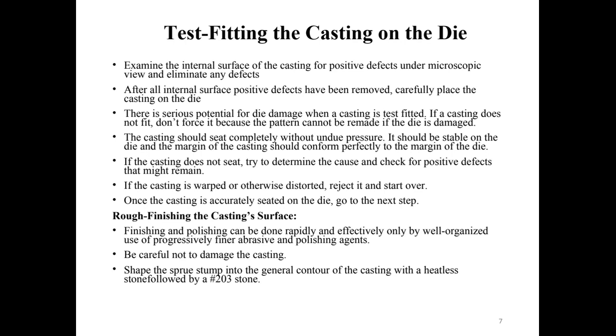If the casting gets warped or otherwise distorted, there is no other solution than to start all over again. So waxing, investing, casting, and all over again. Rough finishing of the casting surface. Finishing and polishing can be done rapidly and effectively only by well-organized use of progressively finer abrasive and polishing agents. In other words, when we're going to start finishing the surface of the coping, we start with the coarse type of burrs and stones going towards the finer burrs and stones, okay?